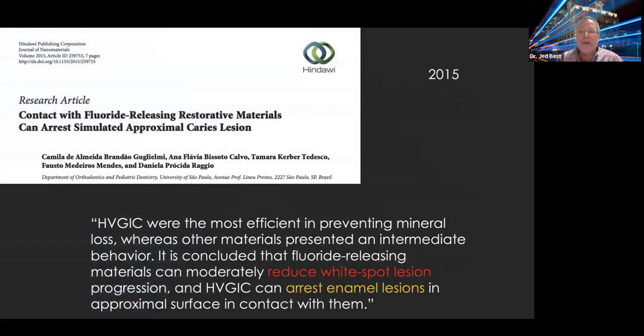Now, interestingly, there was a study done in 2015, so it's roughly 10 years ago, where it basically concluded that the fluoride-releasing materials can moderately reduce a white spot lesion. But the part that's really fascinating is that the high viscosity glass ionomers can arrest the enamel lesions. Why? Because of the fluoride release, as long as they're in intimate contact. So if you're doing a class 2, and the adjacent tooth had a white spot lesion on it, ideally the glass ionomer is the way to go.